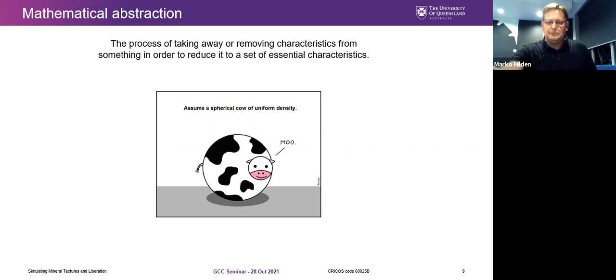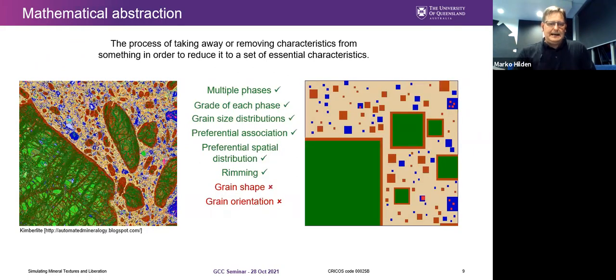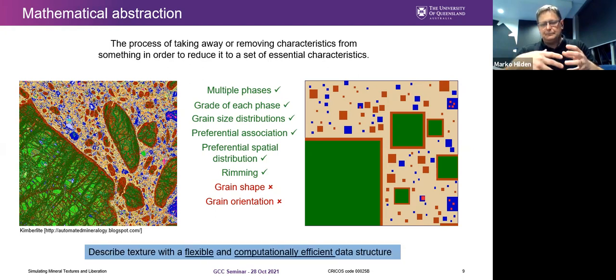To tackle the problem of multi-phase liberation, if we use, for example, the texture on the left, we can create a simple analog of this by replacing the grains with a square shape, and it would still have many of the textural features of the real texture, with the exception of the grain shape and grain orientation. And if it turns out that the shape has a dramatic impact on liberation, then this obviously would be a poor model. If it doesn't, this abstraction would allow us to describe texture with a computationally efficient data structure.